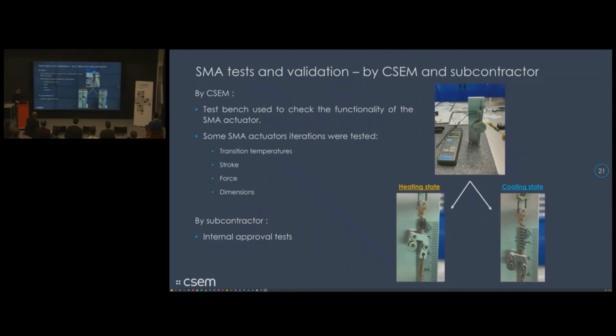This is the preliminary test slide. So after the SMA manufacturing and before the integration of the actuator in our mechanism, we did some preliminary tests. So here the idea was to find the best model for our applications. So we designed a simple test bench, and we characterized all the manufactured actuators. Our idea was to characterize the transition temperatures, the stroke, the force, and the dimensions of each actuator. Thanks to this little test bench, we highlighted some problems with the actuators, and with the different iterations, we solved it.